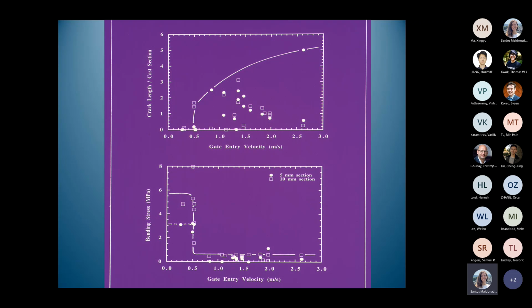These two castings had virtually no cracks. They looked perfect on X-ray, and they could have gone out from the foundry, and the aeroplane could have been hanging from the sky on these two castings, but the strength was not there. They had nearly no strength, but they'd passed all the quality tests. And that result so shook me, I changed all the research at Birmingham on that day for the next 15 years. And we researched the problem of how to get rid of turbulence in castings because of the danger for normal castings. We were living with dangers we didn't even know about.